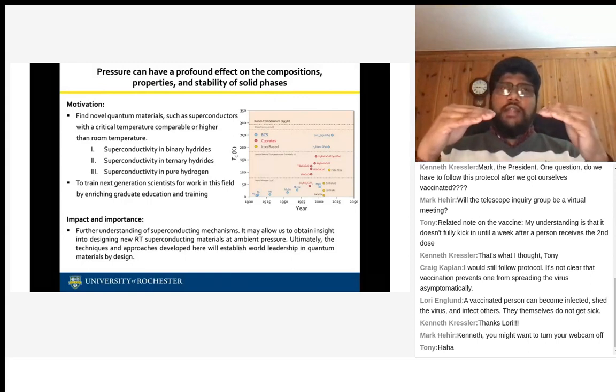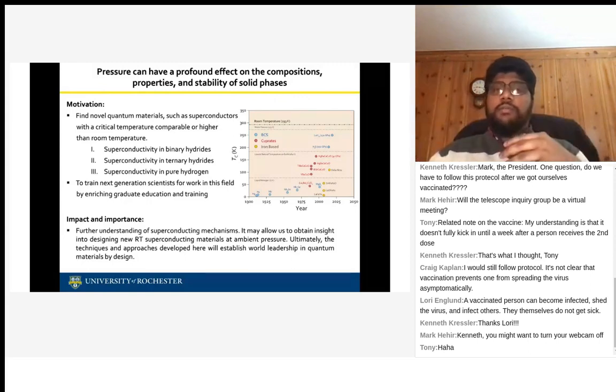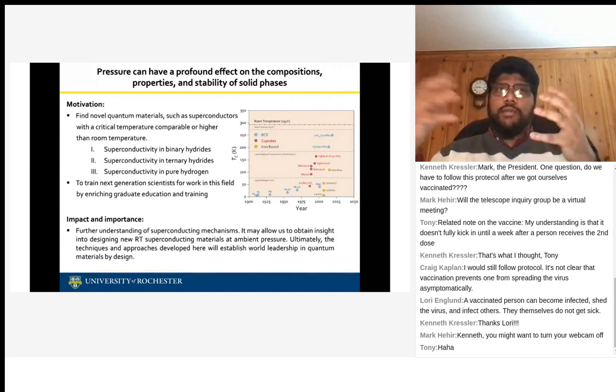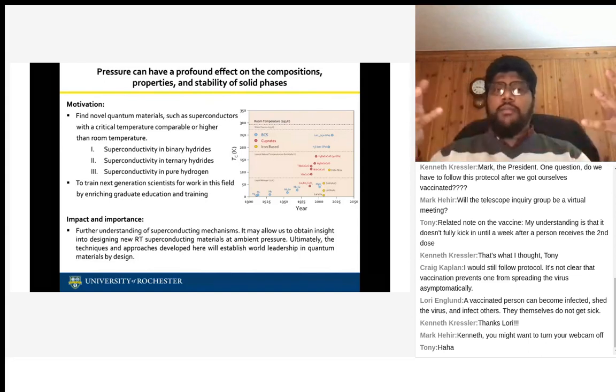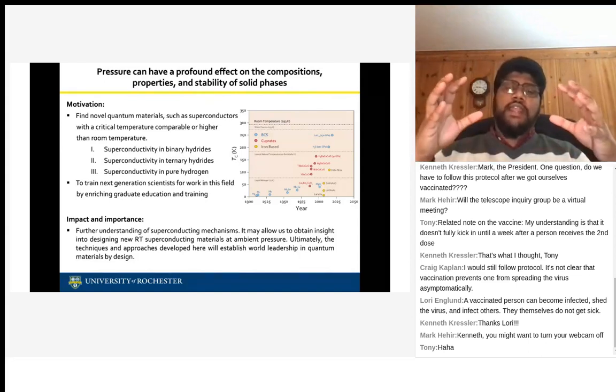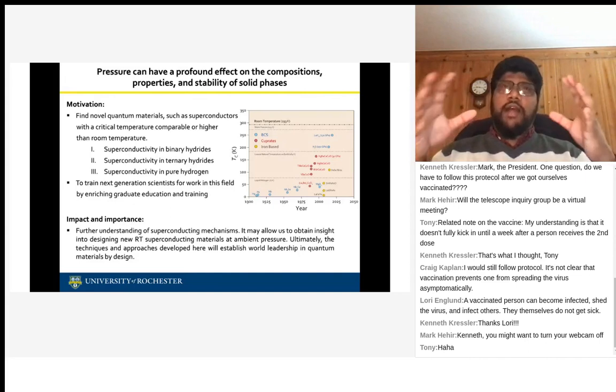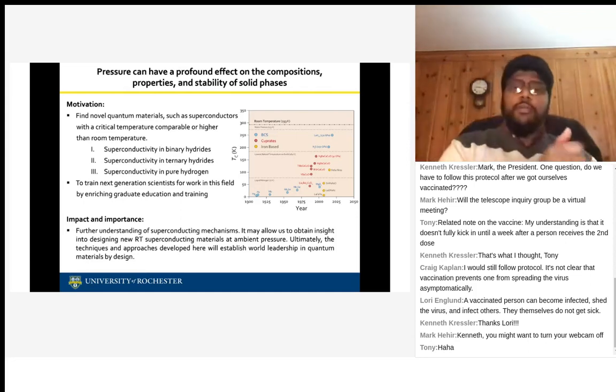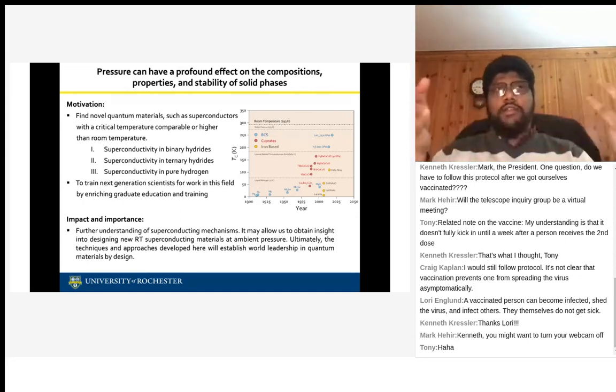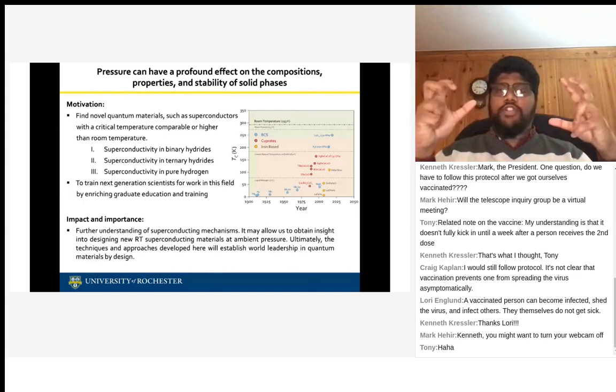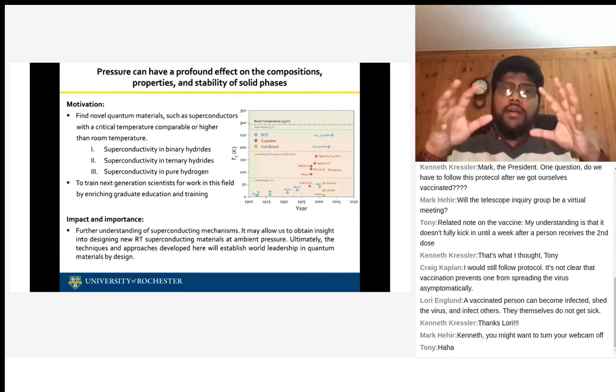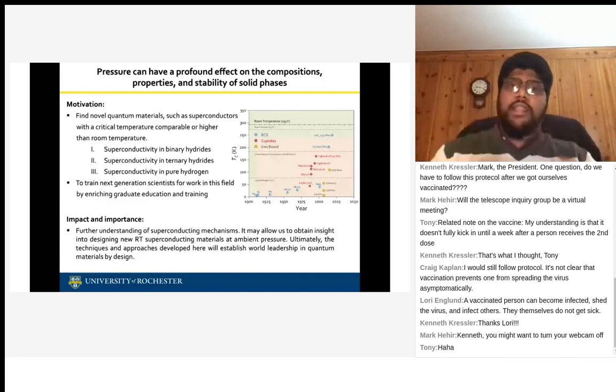But the issue is that to get to metallic hydrogen, you need an enormous amount of pressure, and these are not easy experiments, going into these high pressure conditions and measuring these properties. So we started to think about how we can mimic the same high pressure metallic hydrogen property, a room temperature superconductor, but at much lower pressures. If I go back to one of the slides I used, chemical precompression, the Tokyo subway, hiring some people to push them in to chemically compress it instead of mechanically pressing it, may be a way to go.